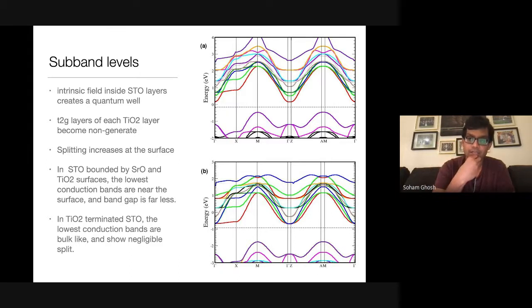And this increases as you go towards the surface. And it also depends on whether your surface is made of strontium oxide or whether it's made of titanium dioxide. So if you have this material, you can either stop the surface at strontium oxide, or you can stop the surface at titanium dioxide. Now, if you stop the surface at strontium oxide, your energy levels, or your bands, would look like the picture on the top, where it's quite non-degenerate. But if you stop the surface at titanium dioxide, the energy levels would become a lot more bulk-like, which is one hint why you have to stop at strontium oxide in order to get a metal.